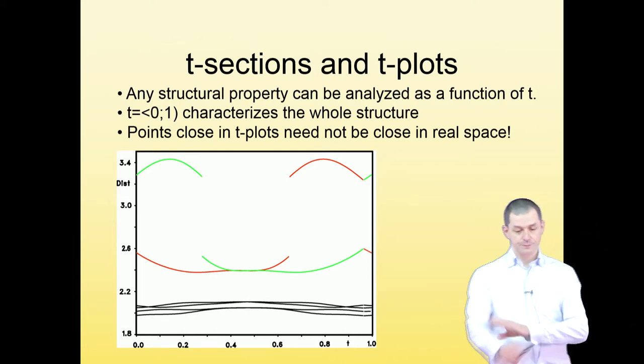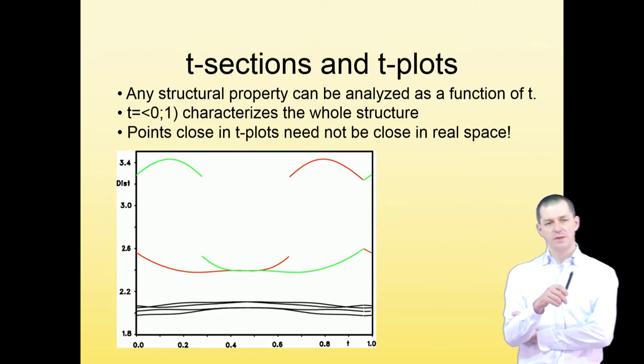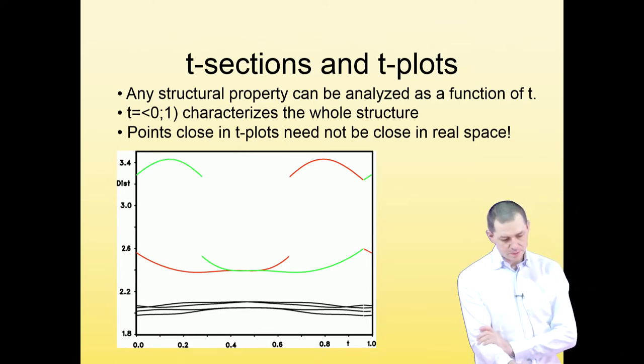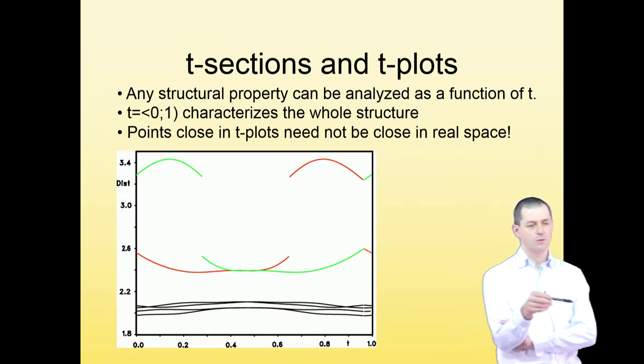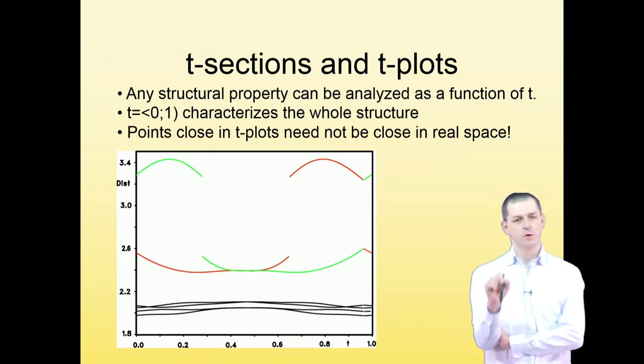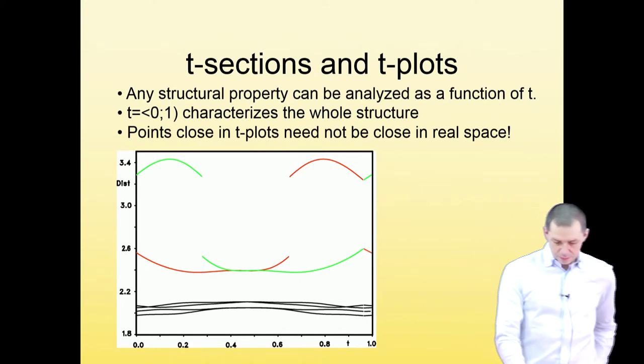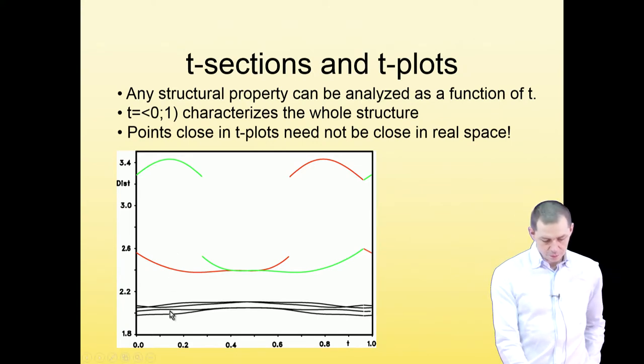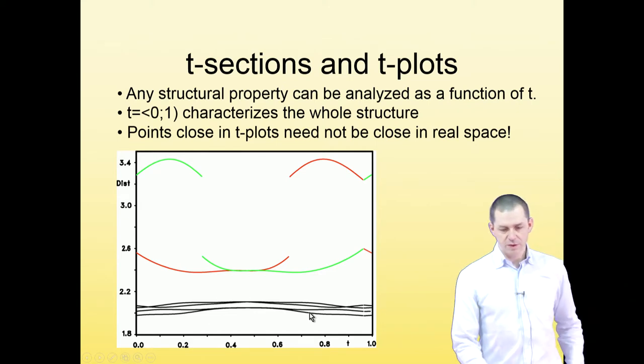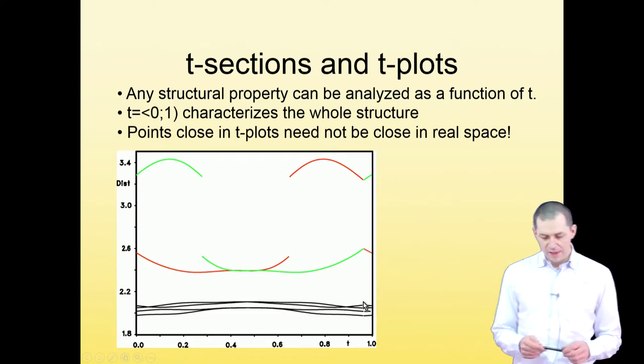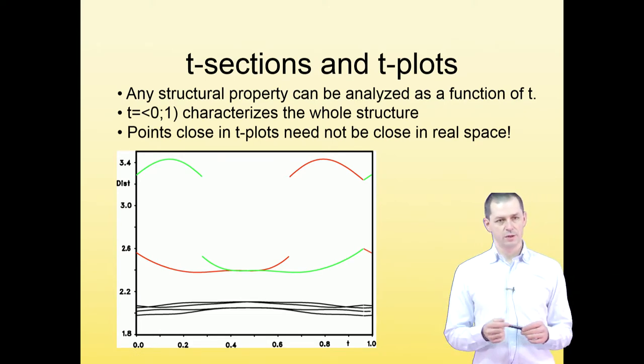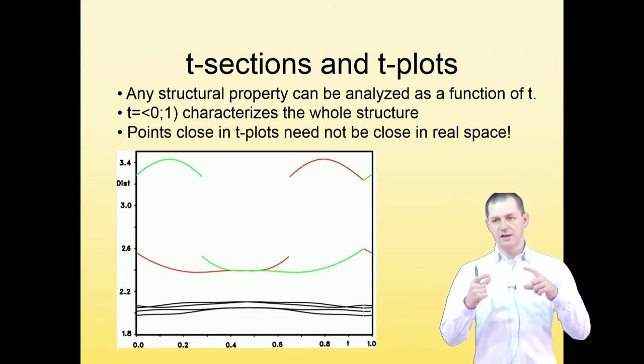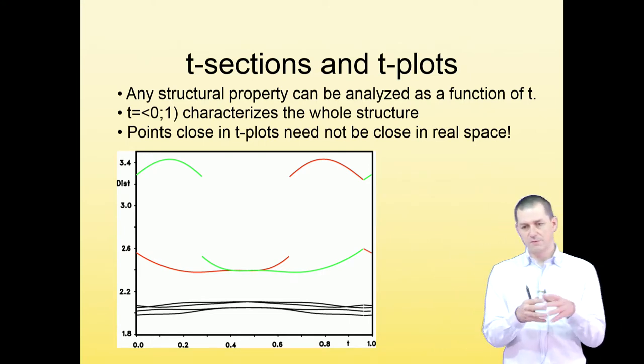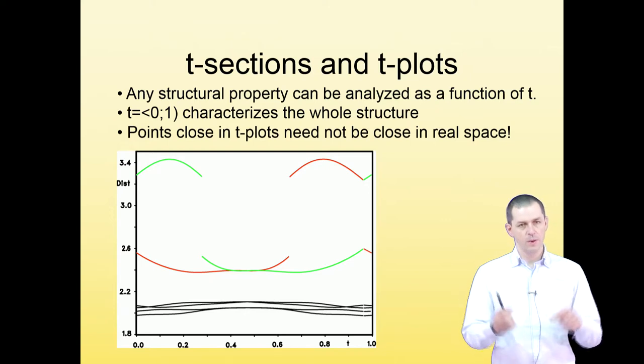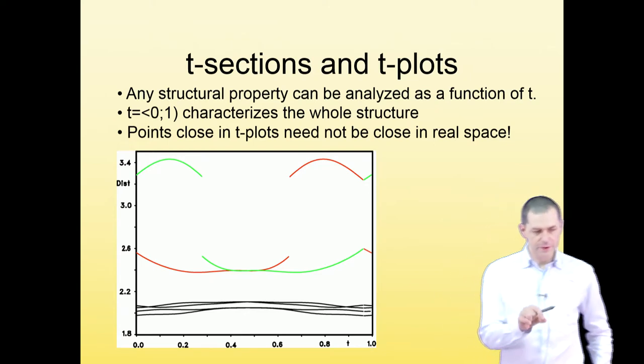So, for example, you can plot interatomic distances as a function of T. And this is an example of one such plot. This is again taken from the structure of chromium diphosphate, and it is the coordination of the central chromium atom in the structure. You can see there are six curves. Four curves are here, and this is the distance, they have very little variation of the distance. So the first thing that you can see from such a T-plot is that four out of the six atoms coordinating chromium have very well-defined and little changing distances to chromium. So whatever is the phase of the modulation, whatever is the environment of the chromium, these four atoms keep the distance in a very narrow interval.